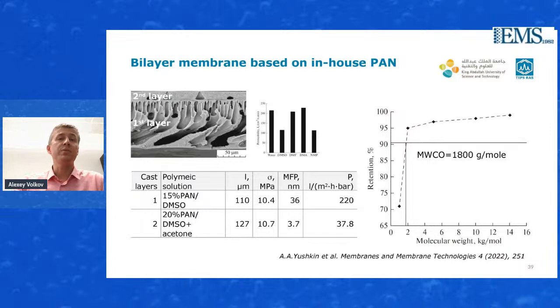And it was possible to reach quite a good molecular weight cutoff, 1.8 kilogram per mole, with of course a reduction of the permeance from 220 for the first layer to 37.8 liter per meter square hour and bar for the double layer membrane.